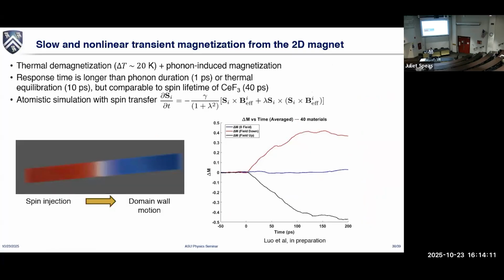So what actually happens within this material, so we did some further simulation, is that this is a very soft magnet. And then at zero field, it actually forms magnetic domains, okay? So you have positive domains and negative domains. If we apply an effective magnetic field, the positive and negative domains respond, but very little, okay? However, a little external magnetic field is really effective in pushing the domain boundaries.